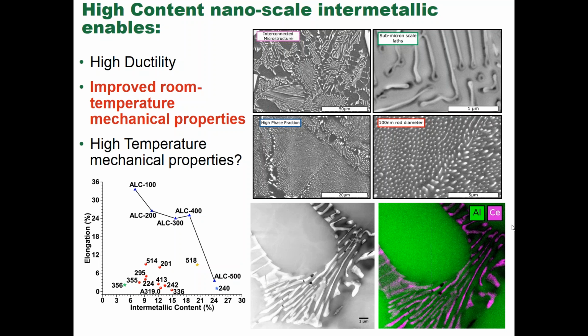If you put too little cerium in the alloy, the microstructure doesn't connect very well, and so you have denuded areas, but typically above about 7% cerium, that does not happen. And really you have sub-micron scale laths that define the shape of that intermetallic. And so part of what we were trying to do is develop a cast alloy that had high temperature properties, and was affordable and was castable.